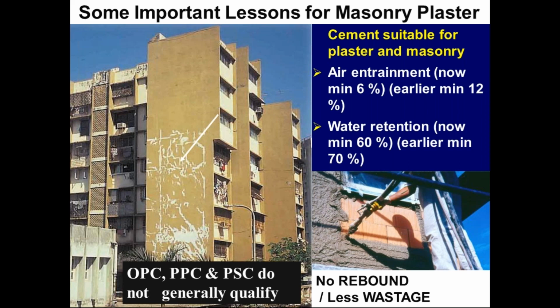Mixed mortar, I have seen abroad being used, and they use a spraying device or a pump to place. You can see the slide on the right hand side. Has no rebound. When we manually do plastering, we get a lot of rebound and a lot of wastage. And then if that wastage is used, you'll end up with a problem of poor quality. So if you can put right chemicals, there will be less wastage and better quality.